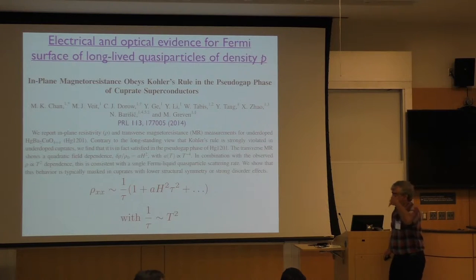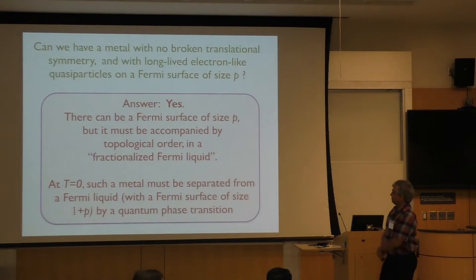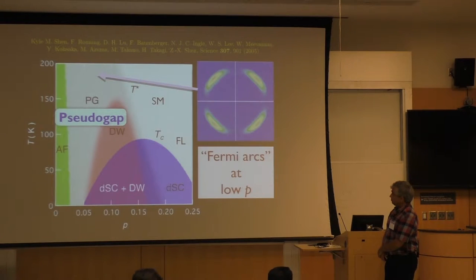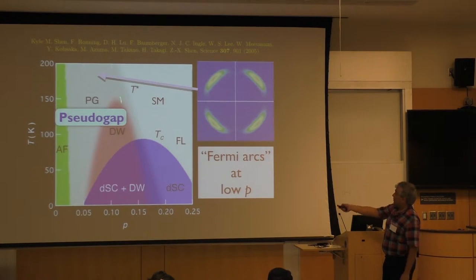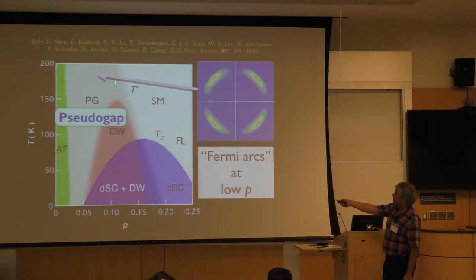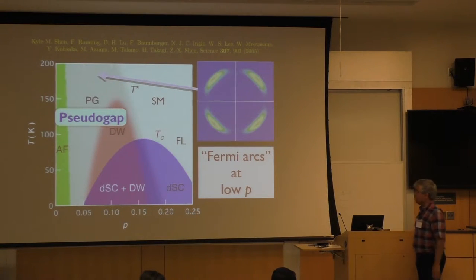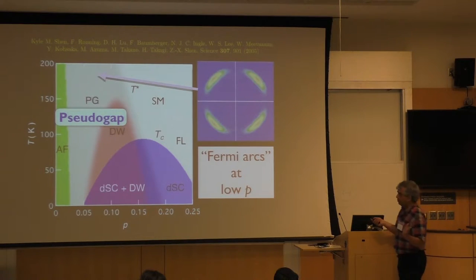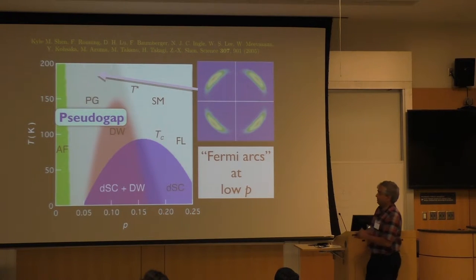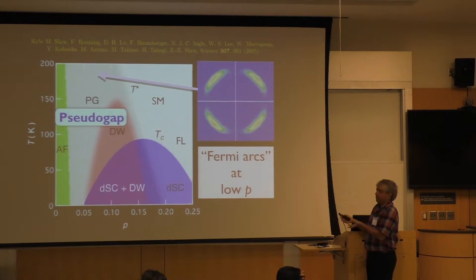The reason we think that must be the case is because of these very beautiful transport properties. These are very low temperature properties of a Fermi liquid. So this high temperature pseudo-gap looks like a low temperature metal, really. If you had some more exotic model with fluctuating orders, the correlation length must be some strong function of temperature, and you would then get highly non-trivial temperature dependence reflecting thermal fluctuations of your order. But you don't see any of that. What you see is actually low temperature quantum behavior of this exotic metal.